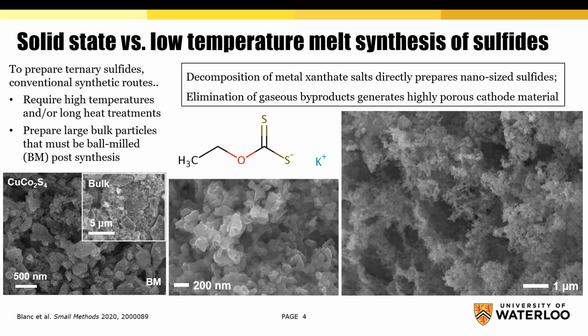Instead, we used a low-temperature melt synthesis through the decomposition of metal xanthate salts in order to directly prepare nano-sized sulfide materials for cathode candidates. The elimination of gaseous byproducts throughout the synthetic methods generates a highly porous network material that ought to promote electrode and electrolyte interaction in magnesium cells.